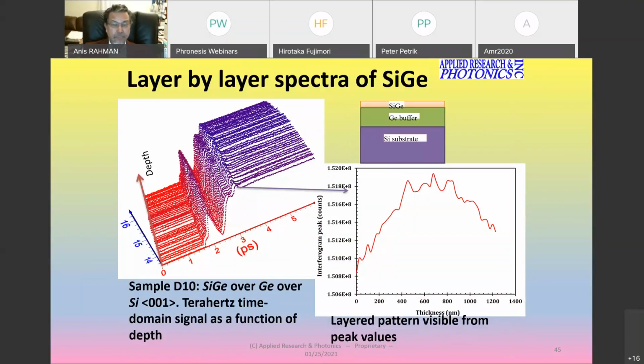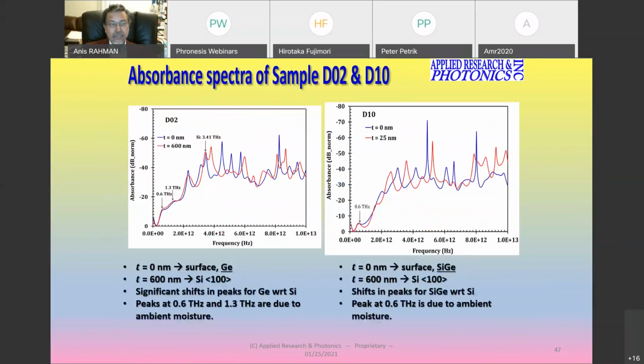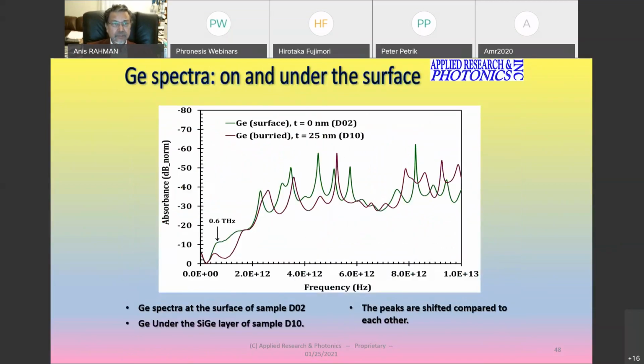And also the other thing, layer by layer spectra, not only image, but also we can go deeper in layers and take spectrum. This is a silicon germanium system, which we have inspected, and these results have been published. So the summary plot is here that we can see the surface, and below the surface of silicon, of germanium and silicon germanium. So germanium spectra on and under the surface can also be inspected. As you can see, there is some difference on the surface, thickness equal to 0, the green curve, and the other curve is at 25 nanometer deeper.